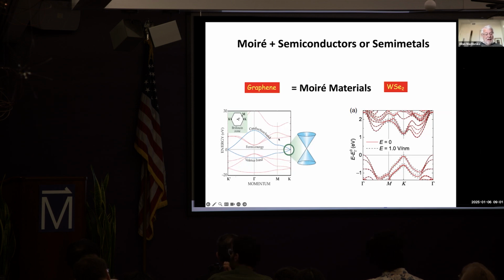And in both of these materials, it will be important in what I'm going to say that graphene is a semi-metal, and that means that all of the low energy states, as indicated by this green circle, are localized in small regions of momentum space. And similarly, in these semiconductors, the low energy states, the states near the Fermi level, for weakly doped systems, are the ones at the top of the valence band, and they are typically near the K point or sometimes near the gamma point in the Brillouin zone, but in either case, they're in little small pockets or valleys, as we call them, in momentum space. And as we'll see, that will be important.